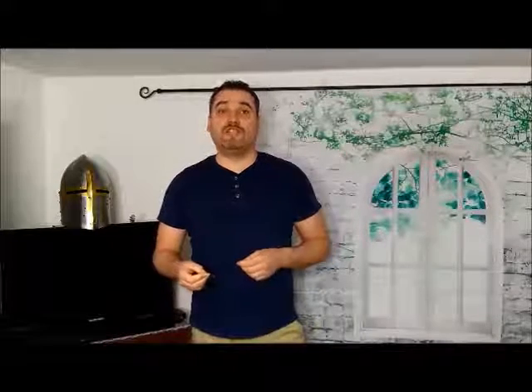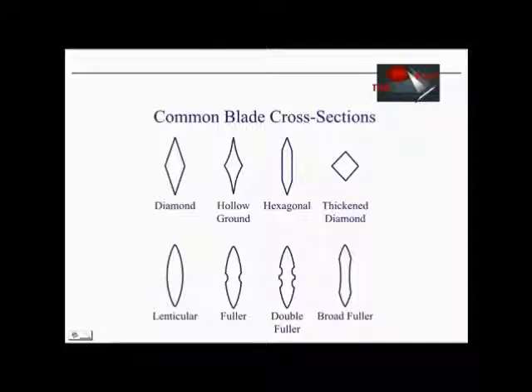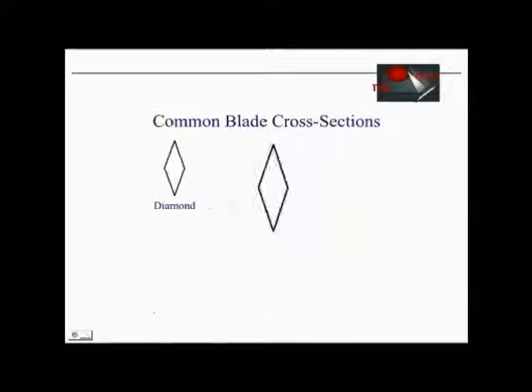There are many more cross-section variants out there, and every one of them has a unique ability. When we talk about the cross-section of a blade, we talk about the three wonders of the sword: thrust, cut, blow. The normal diamond is a pretty simple and straightforward design. It is especially good at giving the blade stiffness perpendicular to the edge line. Therefore, the vibration is reduced and the thrusting ability is increased. However, the blade width from edge to edge is limited, and this can lead to a less strong blade when it comes to direct edge-to-edge impact, which is partially compensated by the higher amount of blade material that can be put to work. The thicker cross-section is not the optimum for cutting though.